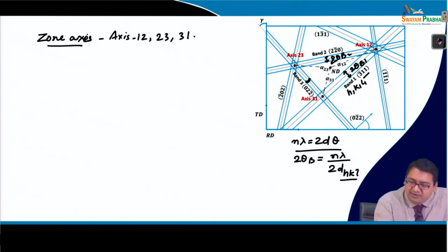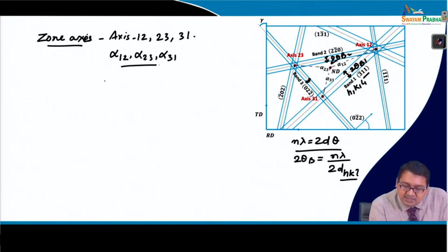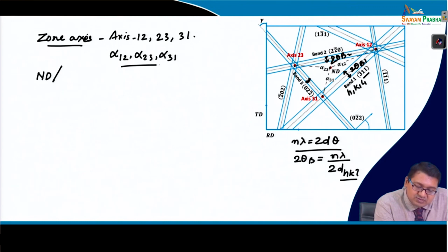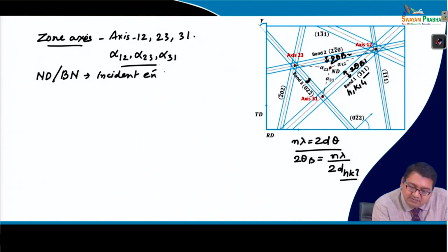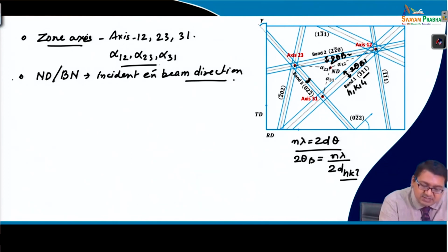So, if we can find out alpha 1 2, alpha 2 3 and alpha 3 1 from the Kikuchi pattern, we can relate this to find out the value of ND, which is also known as the beam normal or the incident electron beam direction, right. So, this is the one thing we will find out, this is the second thing we will find out, and then we will try to find out RD